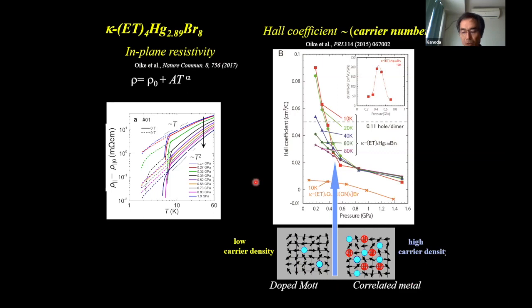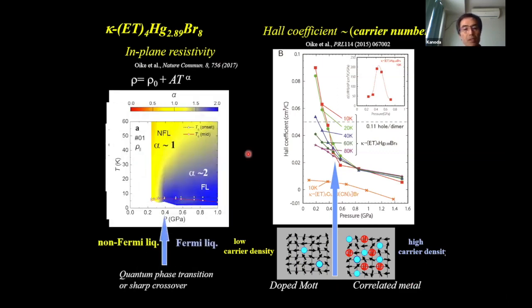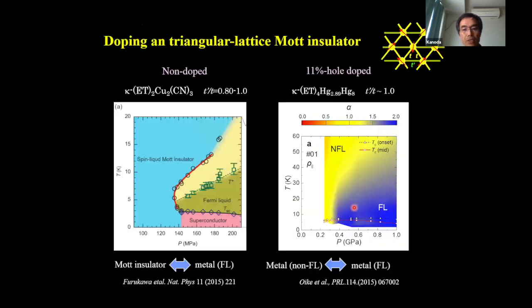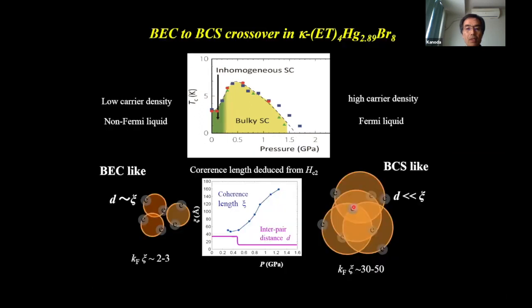And the exponent of the resistivity changes from here to here. This is the exponent. The exponent is unity. This unity changes to 2 if you apply pressure. So this is the non-Fermi liquid to Fermi liquid crossover occurring here. Okay, associated with this crossover, the superconductivity also shows a crossover from BEC to BCS.